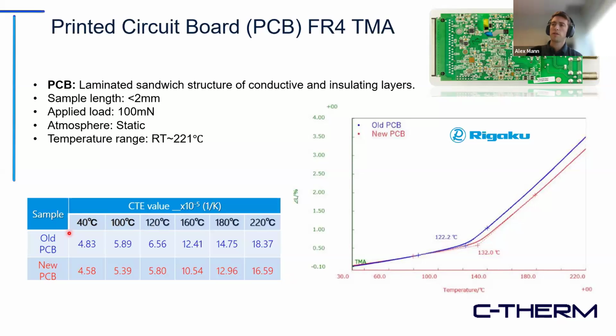Quantifiably, we can look at the CTE values, and we see that around 40, pretty similar; at 100, pretty similar; at 120, we're starting to get a little bit of a difference, and then after that, the old PCB expands a lot more.